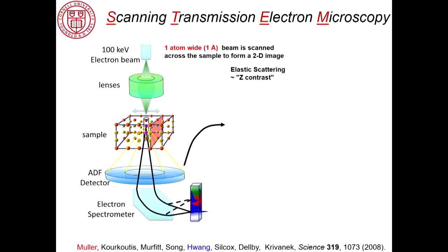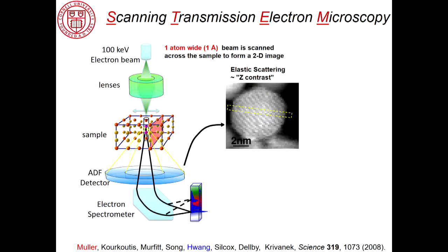So the way people do modern materials electron microscopy is take an electron beam, focus it down to a spot smaller than an atom, and scan it around. Electrons that scatter to high angles, this is Rutherford scattering, form an image. So here is my nanoparticle. And the usual trouble with nanoparticles is they're never straight down the zone axis. They're randomly oriented. This is a fuel cell catalyst particle. So you get a couple of lattice fringes arranged like that because it's randomly oriented.